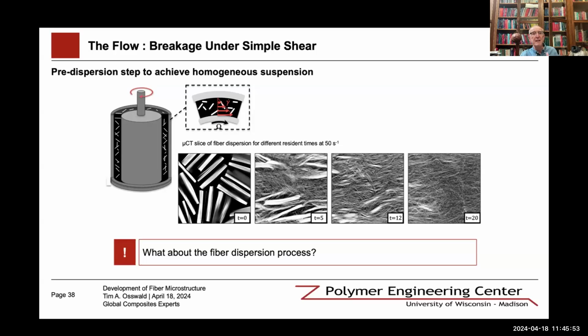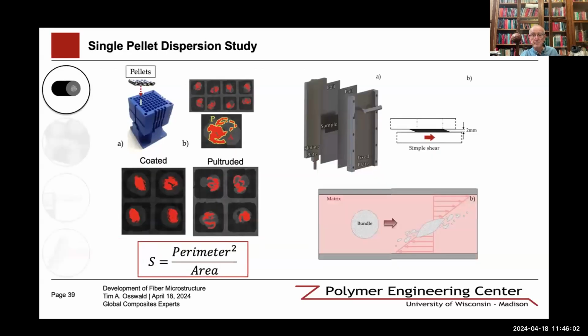So the melting and dispersion is something that occurs in the plasticating unit that has not been looked at in much detail. So the question is, how do fibers disperse? We did a bunch of experiments using a sliding plate rheometer, where we have a simple shear flow and where the fibers get dispersed. And so we analyze the dispersion of the fibers, and we have a parameter S, which is the perimeter divided by the area.